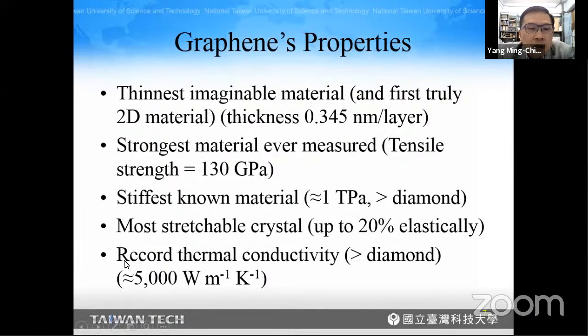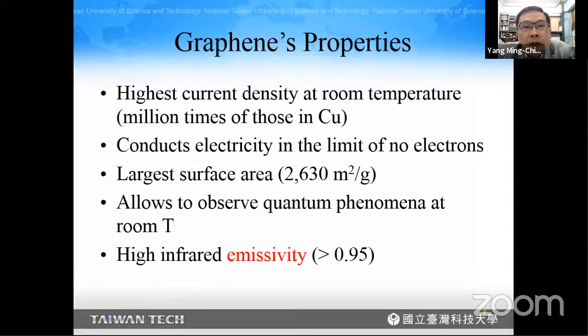Another property is that graphene has a record thermal conductivity, greater than diamond, around 5000 watt per meter per Kelvin. Another property is the highest current density, millions of times that of copper. It conducts electricity in the limit of no electrons. It also has the largest surface area and allows observation of phenomena at room temperature. And graphene has a high infrared emissivity, greater than 0.95. This is important in this study.